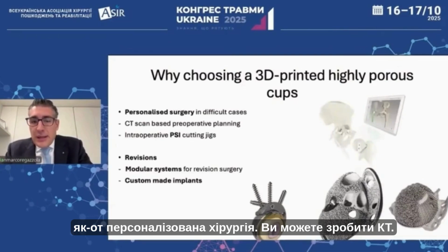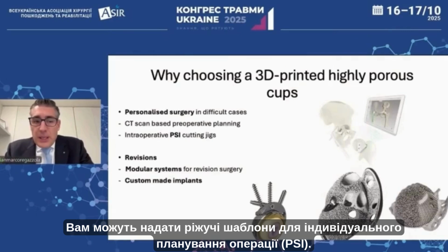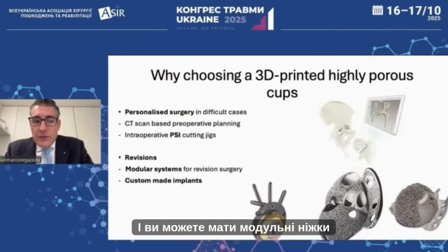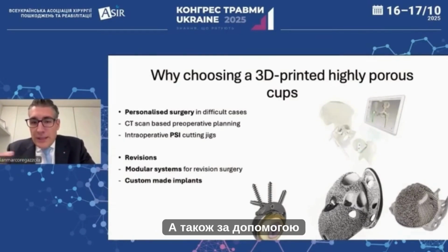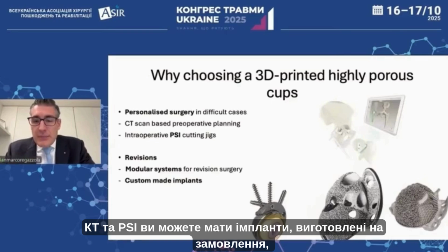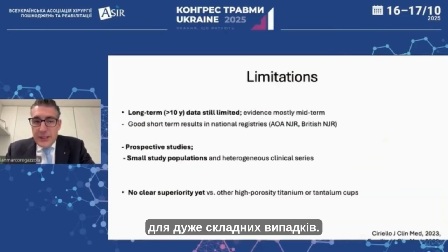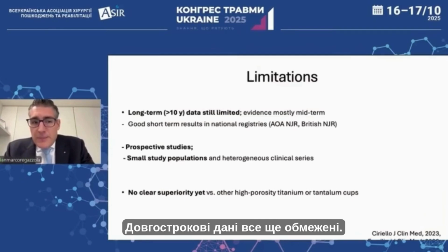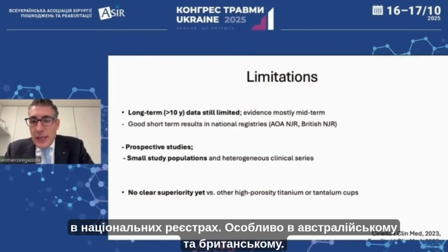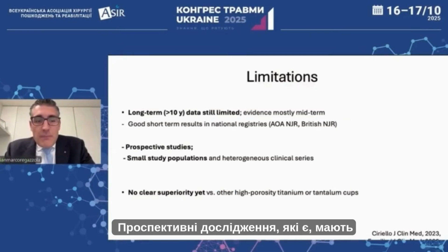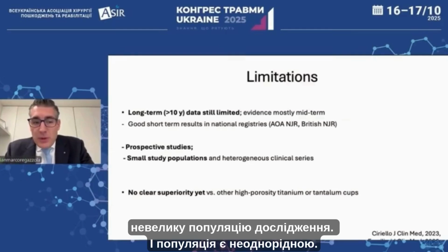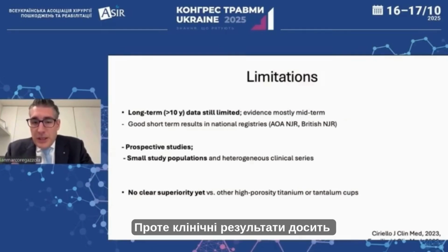You can do a CT scan. They can provide for you PSI cutting jigs, and you can have modular systems for revision surgery. And also with the CT scan and PSI, you can have custom-made implants for very complex cases. Of course, there are limitations. The long-term data are still limited. There is evidence mostly at midterm. We have good results, however, in the national registers, especially the Australian one and the British. The prospective studies around have small study populations, and the population is heterogeneous.